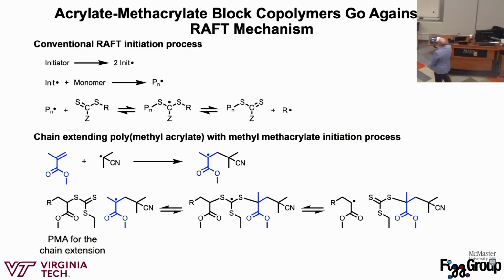Yeah. So if we look at this, what we want to do is get this secondary radical, but we're trying to go through this chain transfer process, which is an equilibrium process, to go from a tertiary radical to a secondary radical. So the tertiary radical is thermodynamically more stable, and we're trying to get to this thermodynamically less stable product. So it actually doesn't work because of the thermodynamics.